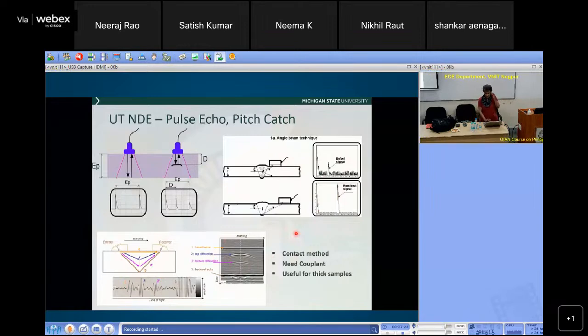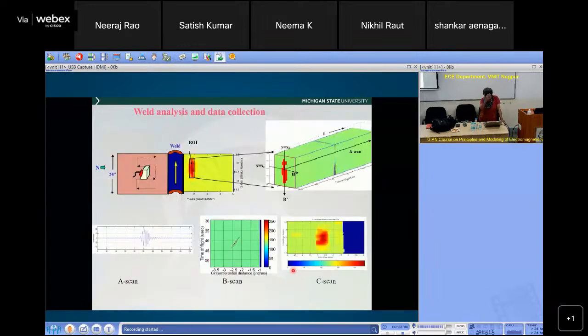Okay, but it's a contact method. How do you couple an ultrasonic wave that is produced in air into the steel? Whenever there is a mismatch in mechanical impedance, there's a lot of reflection. So you need a couplant. And that makes things very slow, and there can also be a lot of variability. The couplant is not the same in this location, and this location produces its own various signals. So it's useful for very thick samples, but those are some of the advantages and disadvantages. I'm going to talk about this a little later. This is the welding.